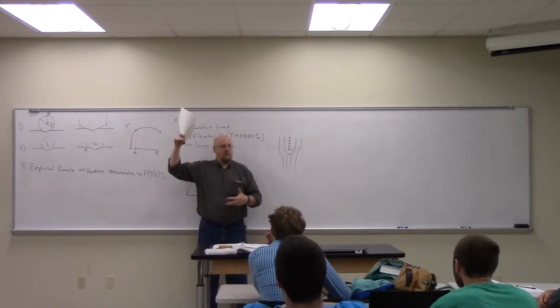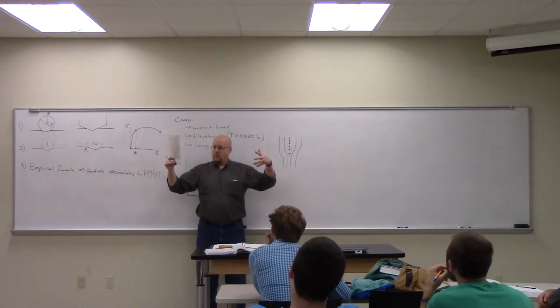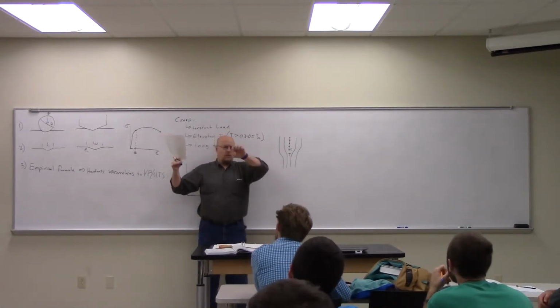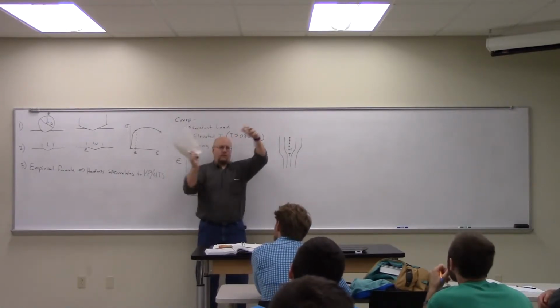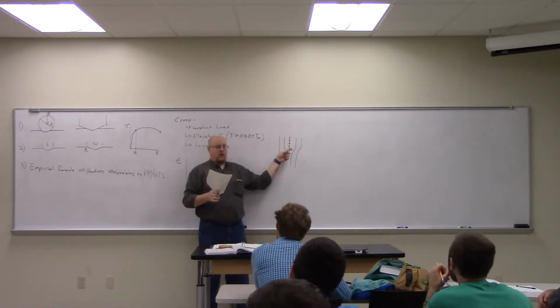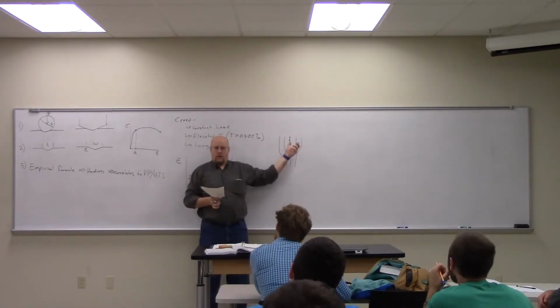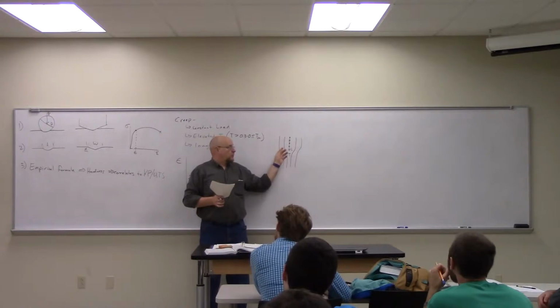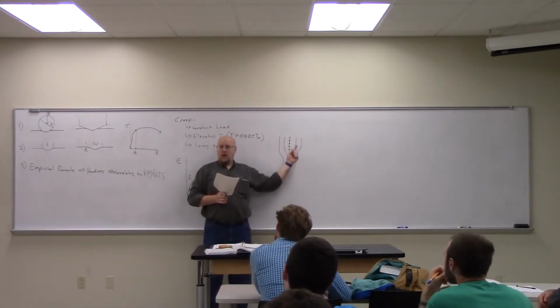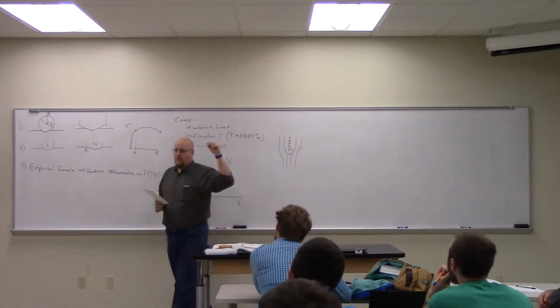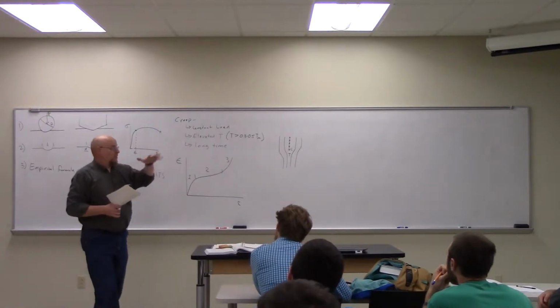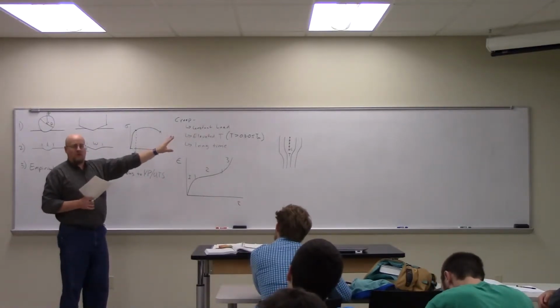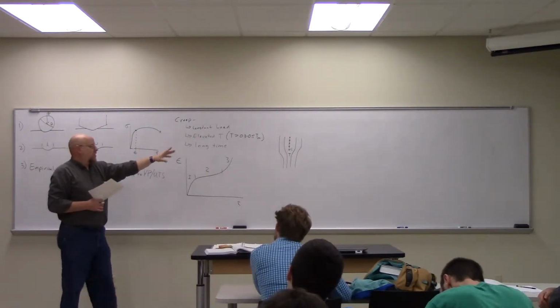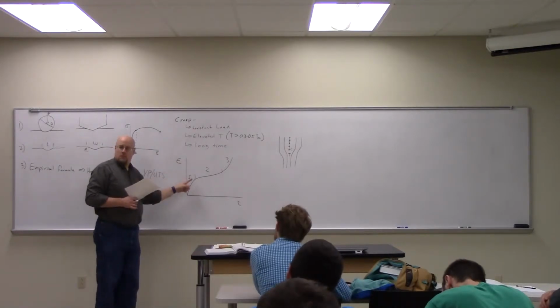All of the bonds are being stretched. You follow what I'm saying? If I pull an atom out, all the other ones are going to collapse and it's going to have a tensile field. Well, tensile and compressive are going to be attracted to one another. And so those vacancies are going to be mechanically attracted to this area and cause the dislocation to climb up. So I'm going to get deformation. I'm going to get change in the alignment of the lattice just because vacancies move around.